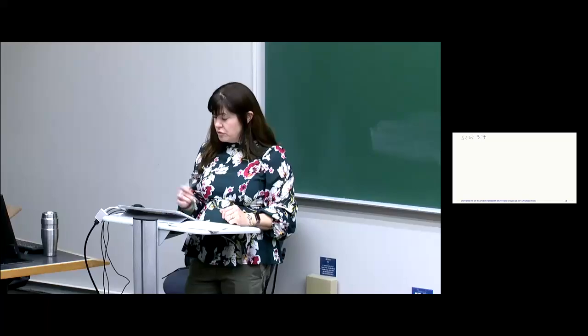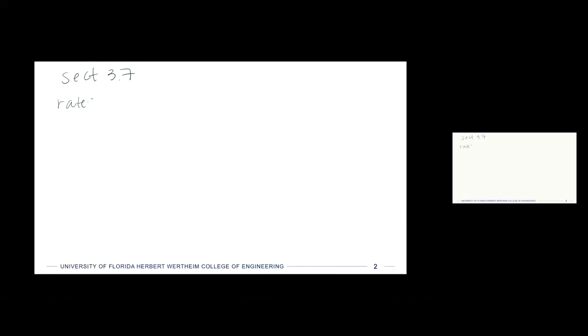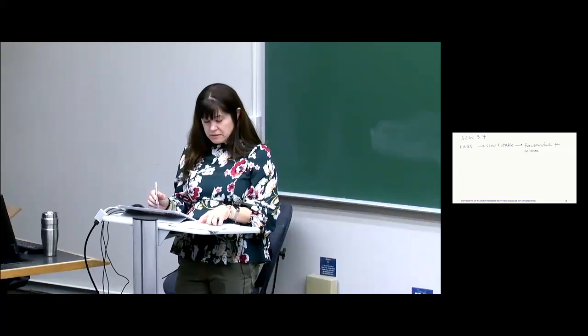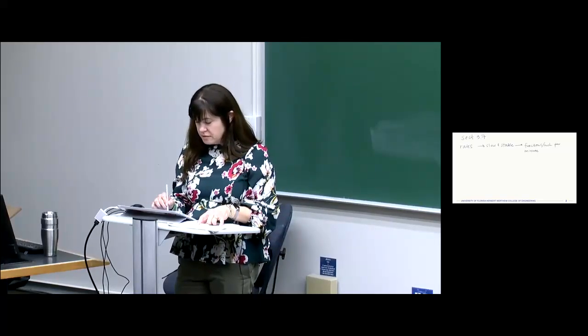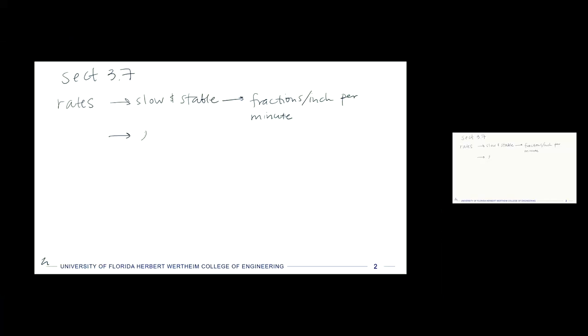There were observed to be kind of two, let's say, rates of failure with cracks. You can have cracks that are slow and stable. When we say slow and stable, we mean something on the order of fractions of an inch per minute. So it is observable that the crack length is increasing, but the whole thing is not going to fail within minutes. And then there was also observed to be a faster rate, which is unstable. These are the crack propagations that lead to catastrophic failure, and that can be hundreds of feet per second.